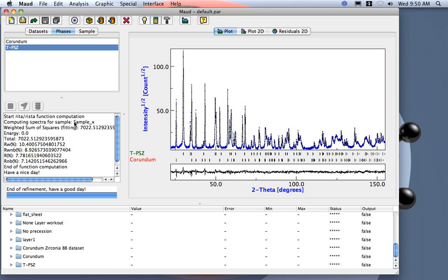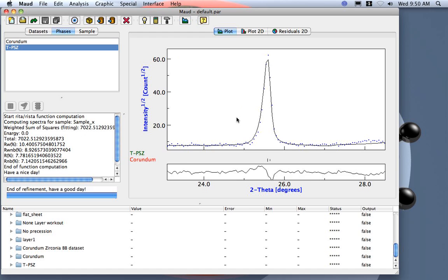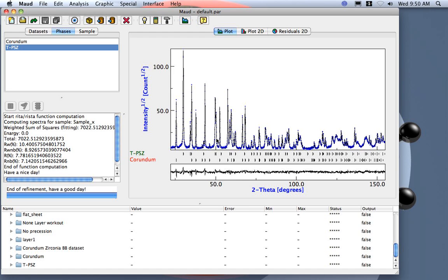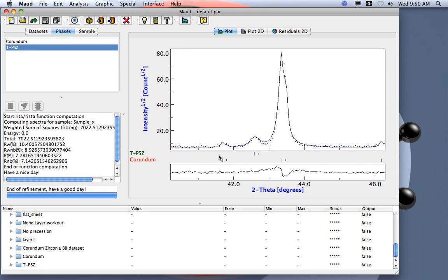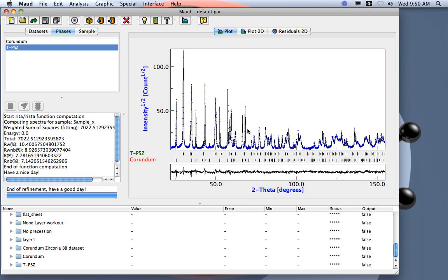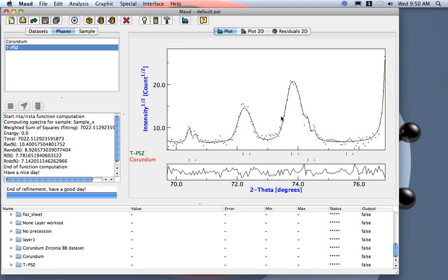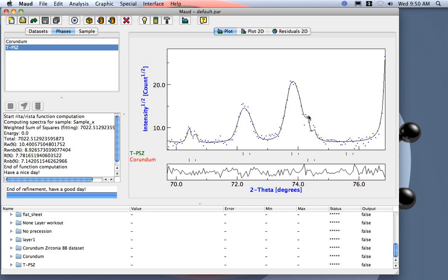It should not change too much. You see, only changing a little bit the weighted sum of squares here. If we want to refine the fitting, it's not really perfect. We can check over here, for example. It's mainly the peak profile not perfect—look over here. So we can do something better actually. Let's check, for example, the zirconia. Here you can see that the peak is a little bit larger. The experimental one is sharper than for the 004, and for the 220.